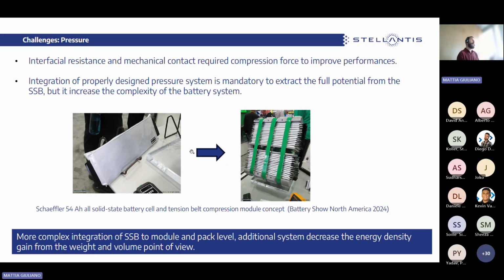Another very important aspect is the pressure, because in order to improve the interface resistance and the mechanical contact between the cell components, a compression force is necessary to improve all this performance. So the integration of a properly designed pressure system is mandatory to extract the full potential from this kind of cell, but clearly it increases the complexity of the battery system. This leads to additional weight and additional volume, which affect the real gain in terms of energy density at pack level.